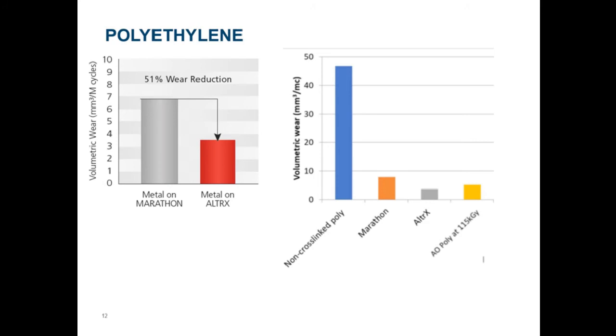When we focus on the antioxidant polyethylene, you get a reduction in wear rates. However, you get a very good oxidative index even under accelerated aging, as I showed before. So it preserves the mechanical properties of the conventional polyethylene, but you get the benefit of a huge reduction in wear rates of the polyethylene material.